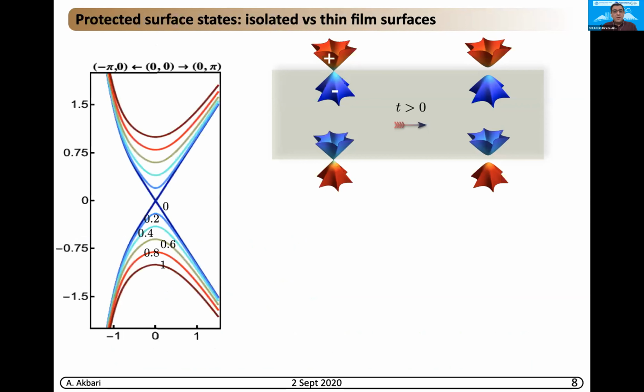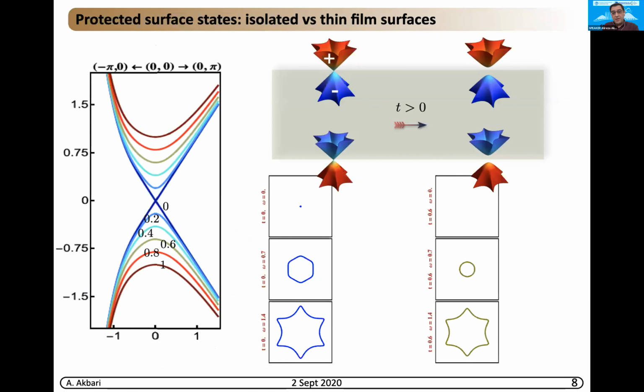You can also look at the dispersion of the system. For the perfect Dirac cone, you see that it's represented at 0, and by adding some constant hopping, you see that a gap opens in the system. Also, if you look at the spectral function of the system, you will see that at 0 T we start from a point, and the spectral function grows and ends up with the snowflake feature at higher energies.